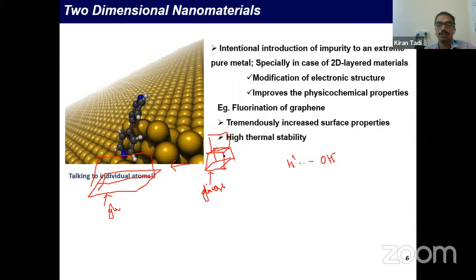The fluorination of the graphene, how my fluorinated graphene is going to affect the electronic structure and the selectivity of my sensor for the sensing of ammonia. If I'm doping this graphene with fluorination about 5%, it is tremendously acting as one of the best receptors for the sensing of the ammonia molecule, due to the fluorine and ammonia interactions.